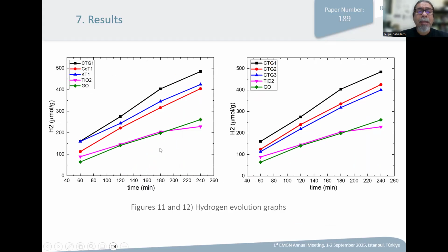And here finally you can see the photocatalytic activity, how the amount of hydrogen produced changes during the time. This experiment is done under ultraviolet irradiation in a closed system, and hydrogen is detected by gas chromatography. Here you can see the amount of hydrogen produced by titanium oxide and also by graphene oxide, and after potassium is incorporated, the amount of hydrogen increases dramatically, and upon incorporation of reduced graphene oxide, that is the black signal, you can see a higher hydrogen production that is attributed to less recombination.